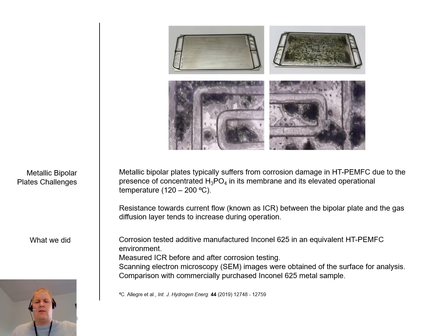In addition, the resistance towards current flow between the bipolar plate and the gas diffusion layer, known as interfacial contact resistance or ICR, tends to increase during operation due to the formation of a passivating layer on the bipolar plate surface. It's therefore important to test the corrosion properties and measure the ICR of samples intended to be used as bipolar plates. We have therefore manufactured Inconel 625 metallic samples using additive manufacturing and tested their corrosion properties. In addition, we have measured the ICR before and after the corrosion tests. We have obtained scanning electron microscopy images for analysis before and after the corrosion tests, and we have compared this with commercially purchased Inconel 625 metal samples.